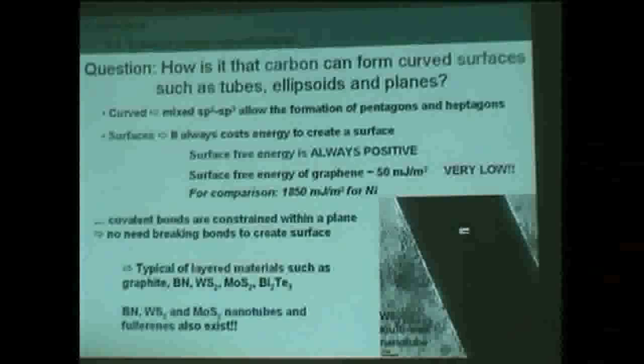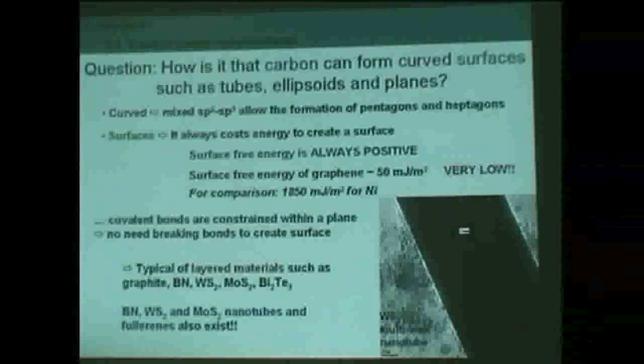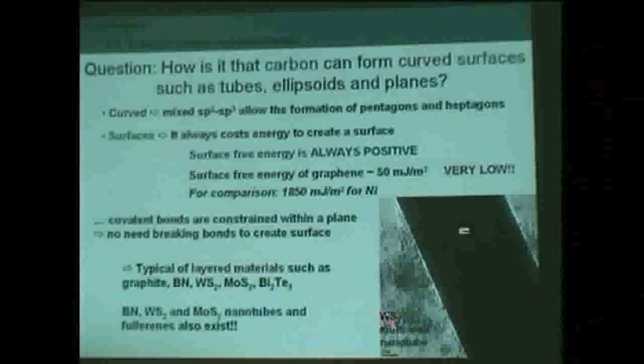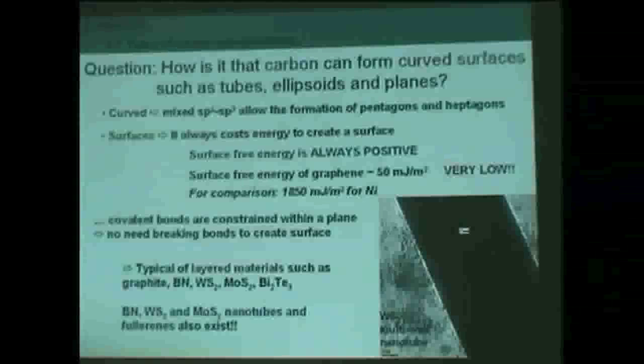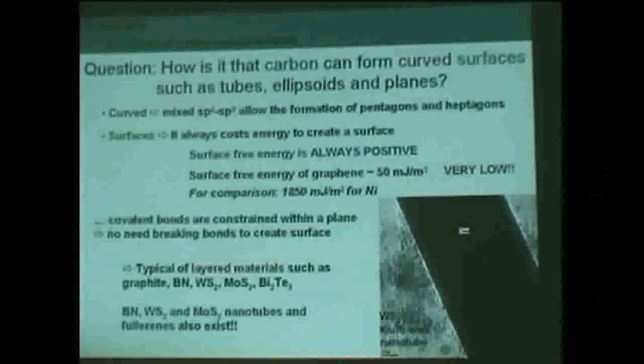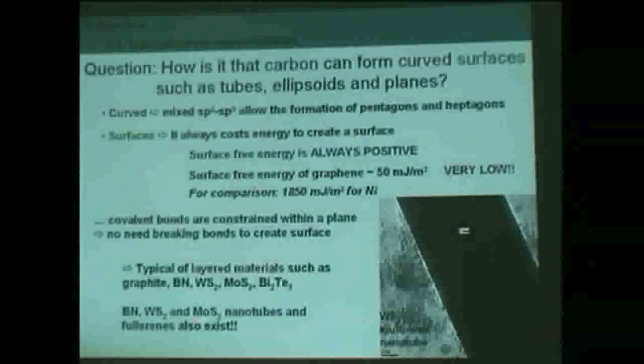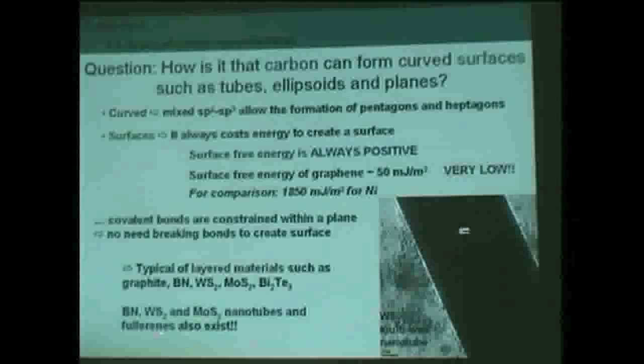And many people thought, well, we could make nanotubes and fullerenes with them, maybe. And they succeeded, actually. Here's an example of a tungsten disulfide nanotube. You've got this hollow tube, and here a multi-layer of the tube - a carbon nanotube, but made of tungsten and sulfur. And fullerenes also - I showed no pictures, but there are also fullerenes of those materials. They also exist.